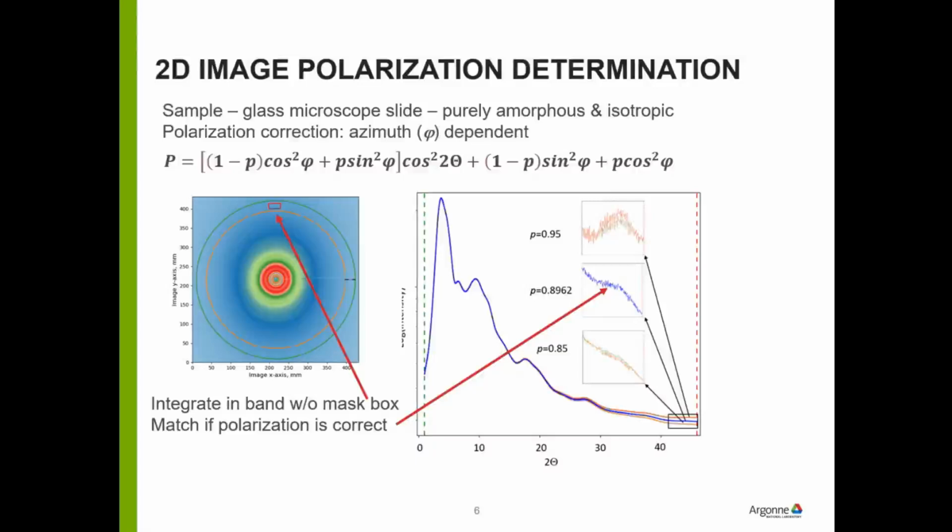You put a little crystal in there and you rotate the crystal around, and you measure the intensity as a function of the azimuth angle off a particular plane, and the variation then gives you the polarization correction. That's a horrible way to do it, because you have to put this funky little apparatus on your beam line and drive it around measuring this remotely, because you can't be in the hutch while you're doing it, and so forth.